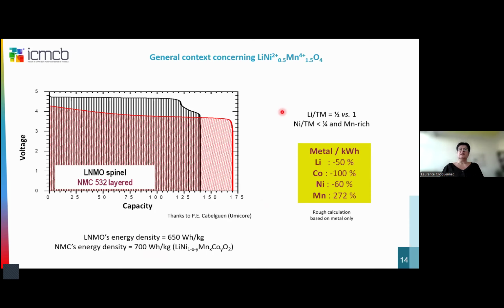You can see that here, contrary to NMC, we have a lithium over transition metal ratio that is 0.5 versus 1 for NMC, and we have a nickel over transition metal that is smaller than 25% and manganese-rich versus often more than 60% in an NMC. So in fact, if we consider the metals, you can see here that we have a decrease in lithium content of 50% for this chemistry. Of course, no cobalt, a decrease of 60% in nickel, and of course an increase to compensate in manganese. So of course this material is highly attractive.